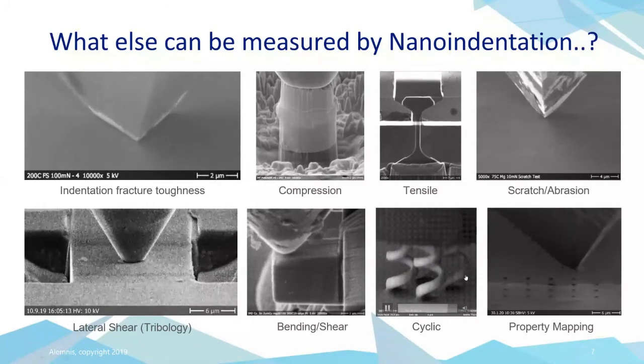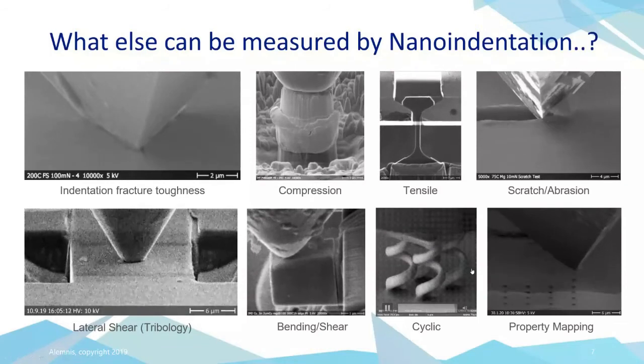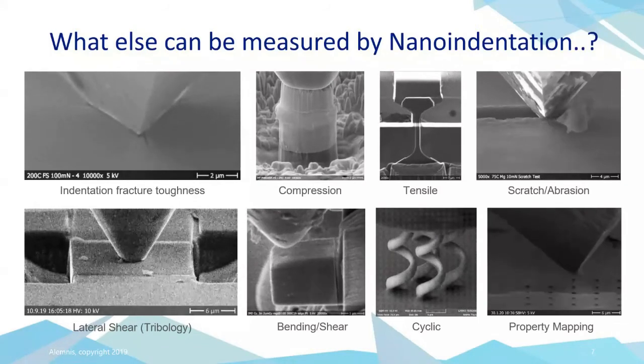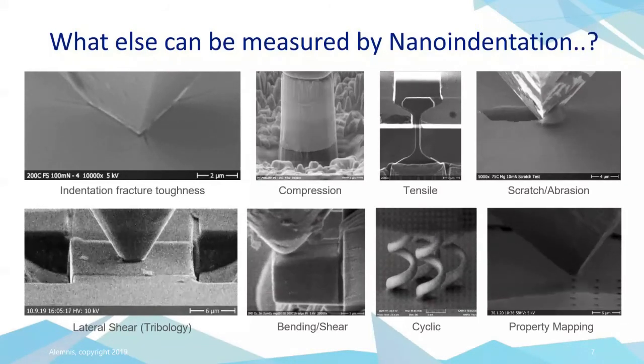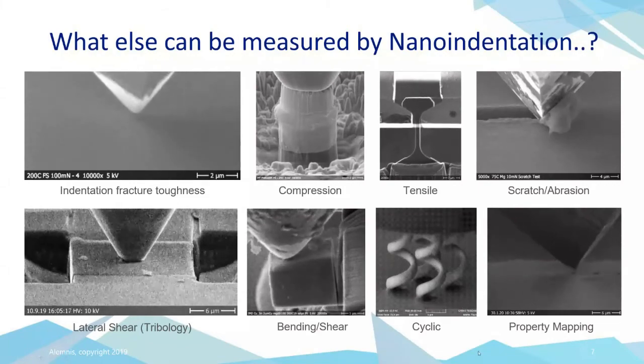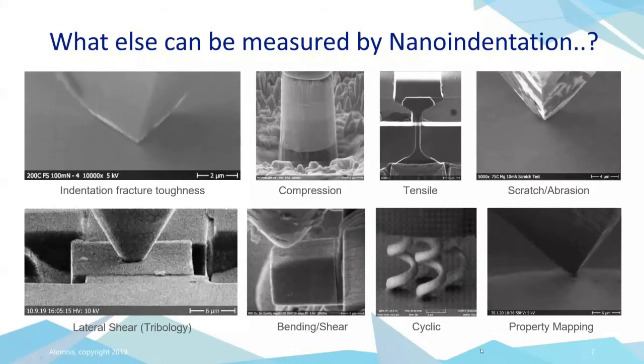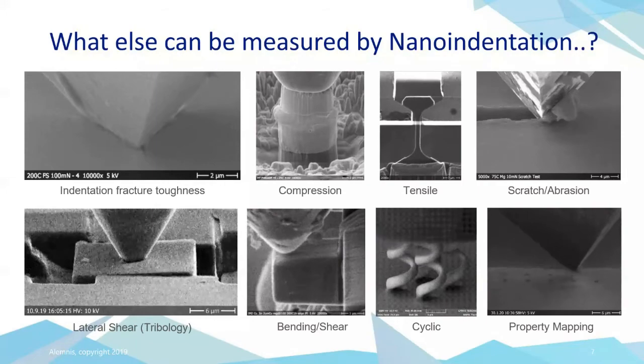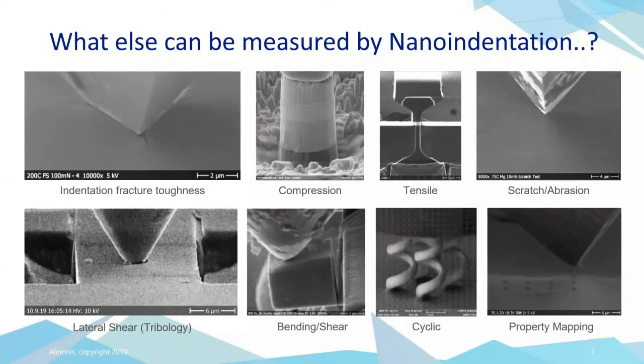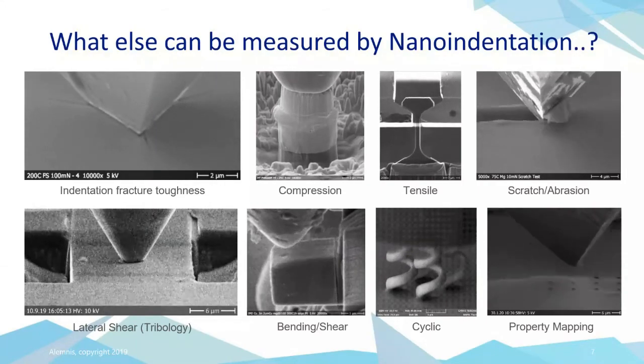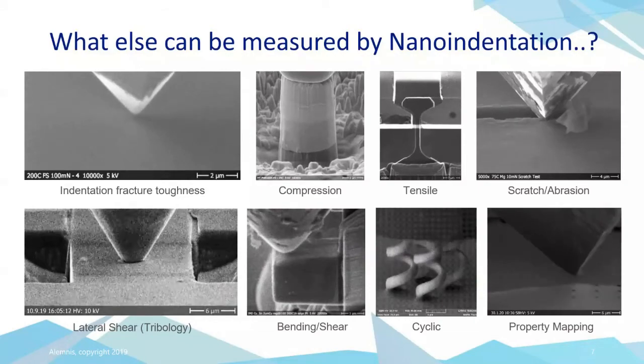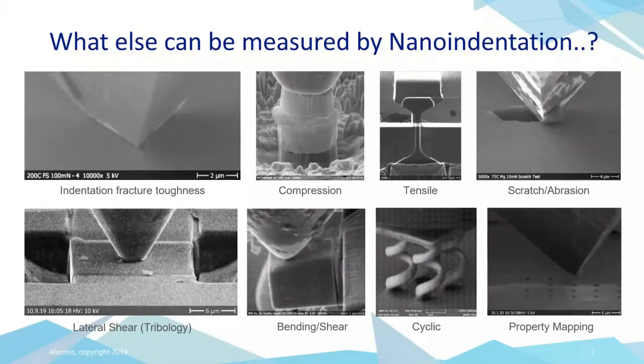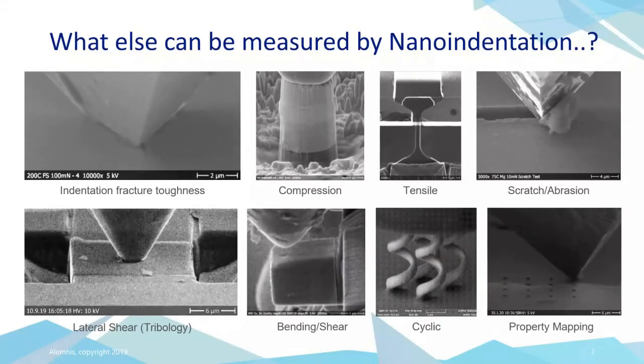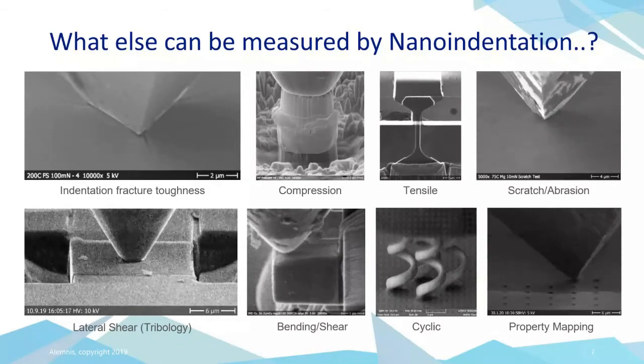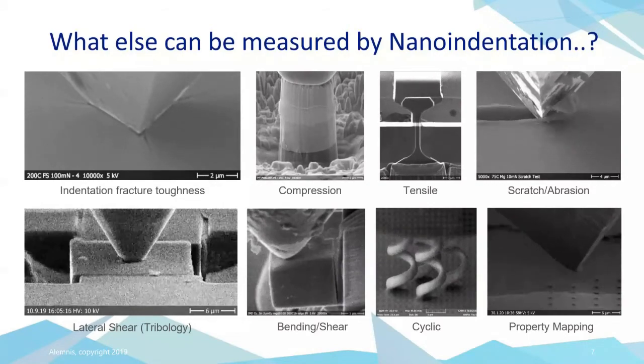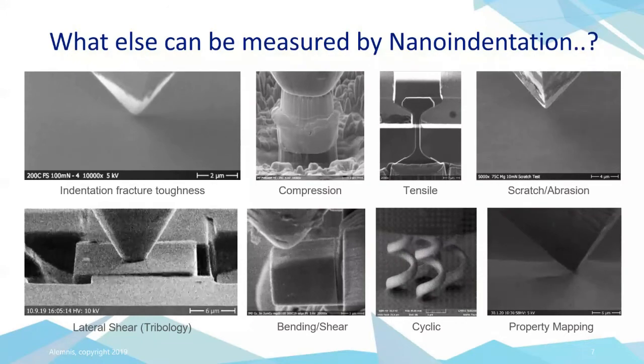Cyclic indentation testing. So here we're looking at a 3D printed structure, very small, and we're actually doing a cyclic indentation test. The advantage of instrumented nanoindentation is you can program the indenter to do whatever you want. It can do a single cycle, a multi-cycle, a sinus mode cycle, a dynamic test, a pause, a creep test, a stress relaxation experiment. Highly programmable to do basically whatever you want it to.